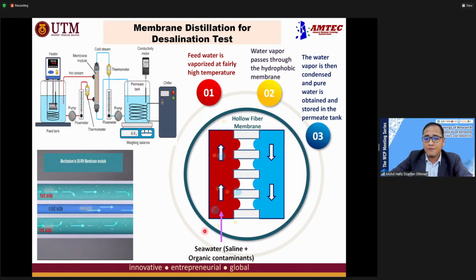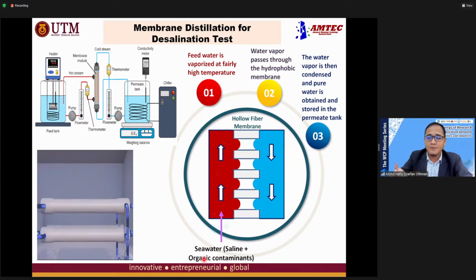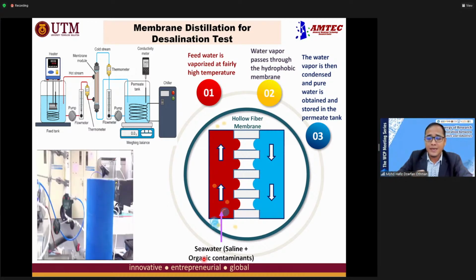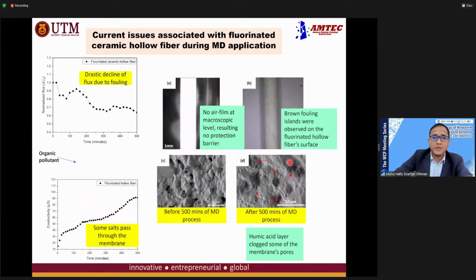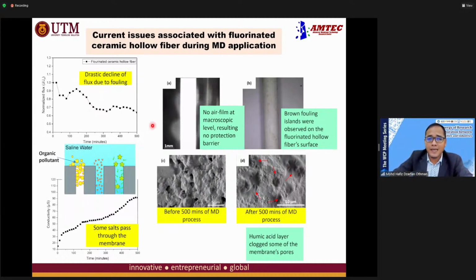So we can have the hot feed, which we increase up to 90 degrees Celsius. At this temperature, some of the water can be turned into vapor and it will be allowed to pass through this hydrophobic membrane. In the cold feed, it will be condensed and we can produce high quality water in liquid state. Using this hydrophobic membrane, we tested with saline water that also contains a organic pollutant, which is humic acid.